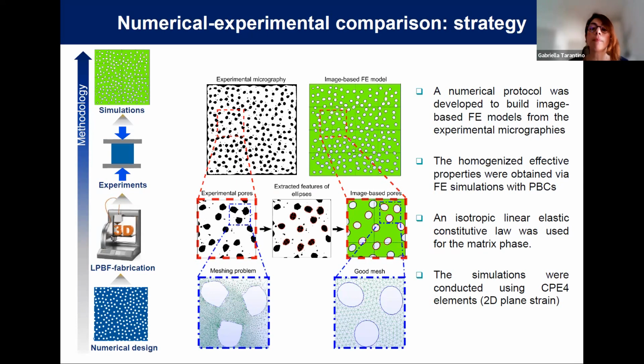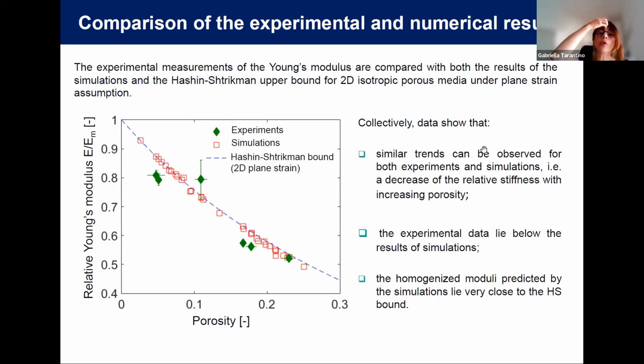And for this reason, we developed an image-based finite element protocol, which allows us to transfer the experimental micrography into an image-based finite element model. I'm going to spare you the details of this process, but the reason for that is that we have seen that a numerical model is not by any means exhaustive or representative of the real microstructure. And so, as a summary, before jumping to the conclusion, we could see that the comparison between the experiment and this simulation, which we carried out in linear elasticity and using periodic boundary conditions, is pretty good. And one striking feature of this material, that it still preserves in 3D, is that it approaches the Hashin-Shtrikman bound, which is known to be the tightest possible bound for isotropic porous media.